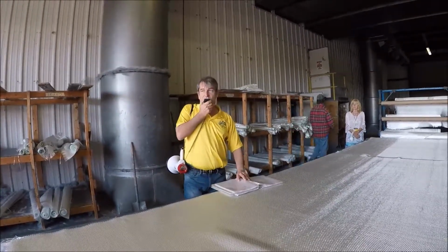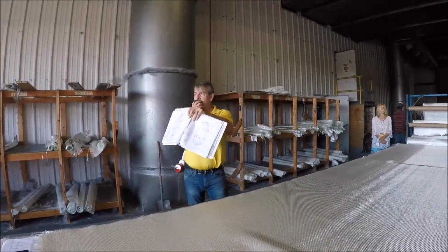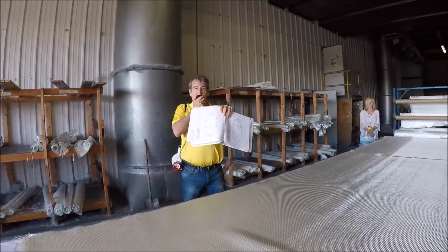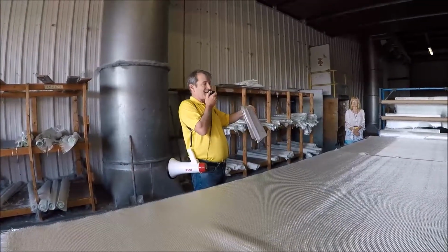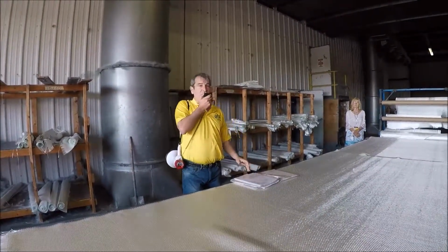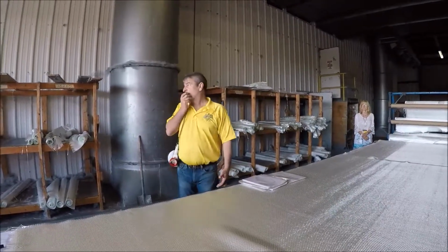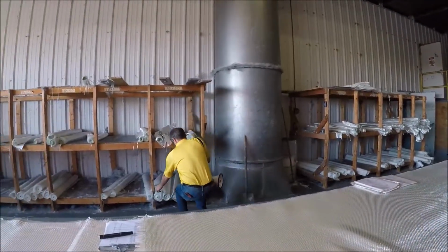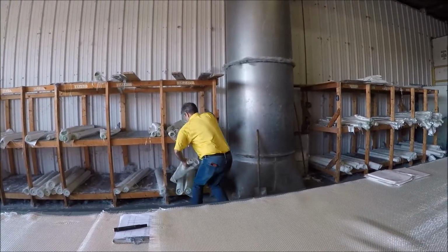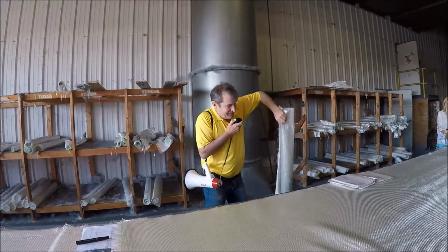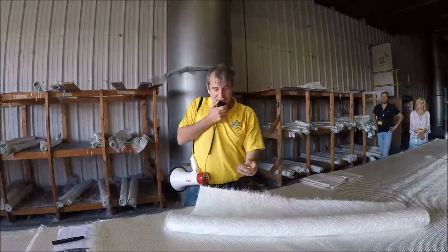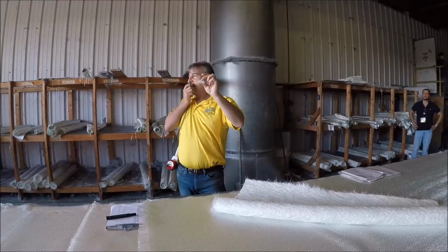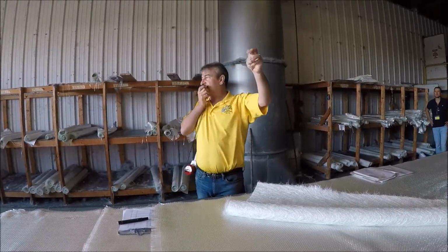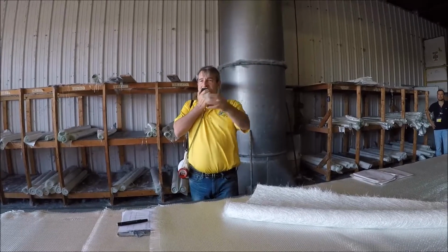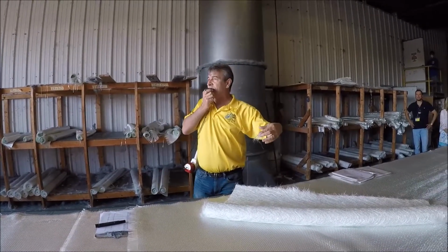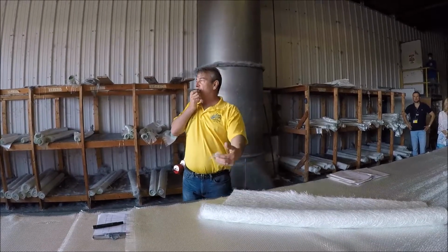So for every model pool, we have a cut book. And that cut book tells the people how the layers of glass are going to get laid out for the pool. There's 2 types of pool fiberglass. One is called chop strand mat. So here's a roll of it. And this material is made on a conveyor belt, and it's chopped up little pieces of fiberglass. They come down a conveyor belt, they're sprayed with a binder, they're pressed flat, and then they're rolled up.